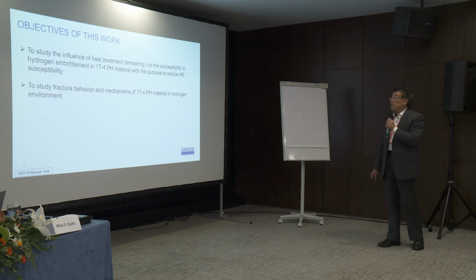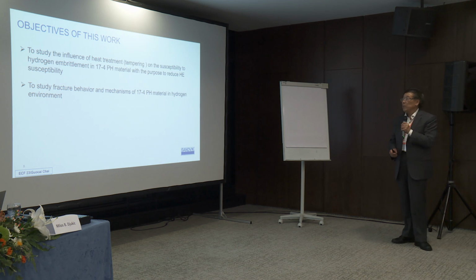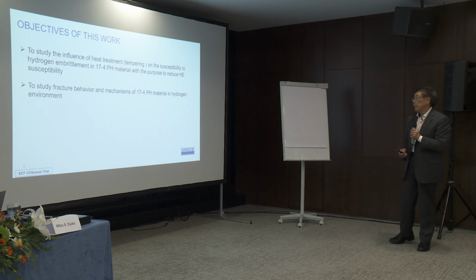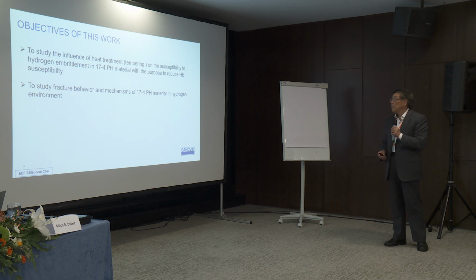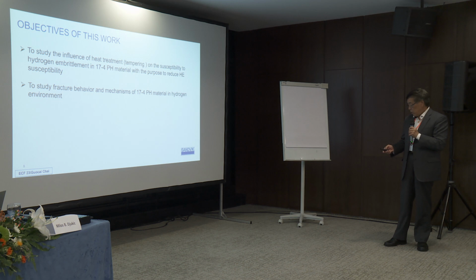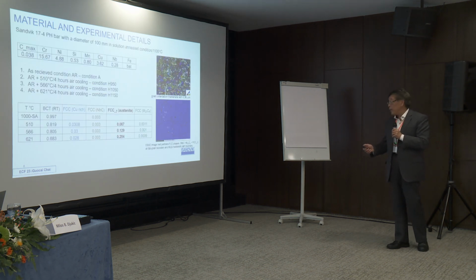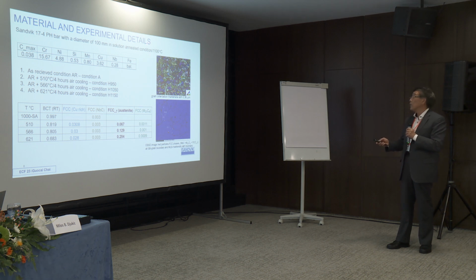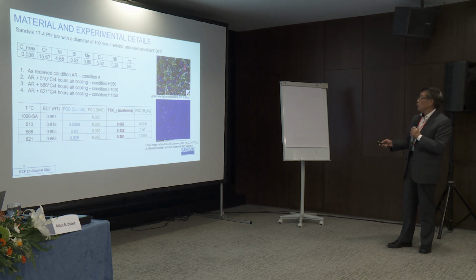So the objective of this study is to find a heat treatment that can reduce this hydrogen susceptibility, and also to try to understand the hydrogen embrittlement mechanisms in this area. So what we do, first we use a very standard material. It's a bar material, solution annealed with this standard composition. Here is the microstructure, quite homogeneous without much texture. The martensitic lath is 0.36 micrometer, so it's quite a good microstructure. Then we use this as-received material and perform three temperings.